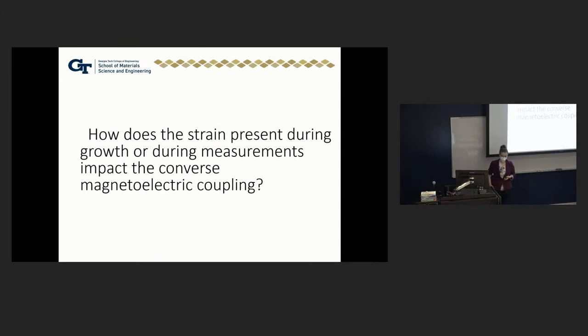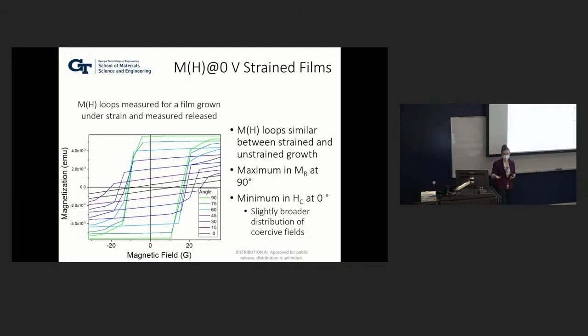Okay, so now that we have this baseline, we understand what's occurring in the converse magnetoelectric coupling in our standard sample without any strain present. So the question is, what happens when we introduce strain either during growth or during measurements? So we repeated the whole thing again. In this case, we took MH loops of films that were grown under strain and measured without it, right?